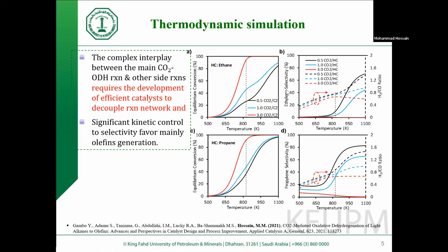To do that, one can consider thermodynamic simulation using the Gibbs free energy minimization approach. Here you can see two sets of plots. The first, A and B, is for ethane, and the second, C and D, is for propane. We can see clearly that as temperature goes up, ethane conversion goes up, and similarly for propane. Also, if you see the three curves, red, blue, and black, with increasing CO2 to hydrocarbon ratio, higher conversion can be achieved at lower temperature. However, the issue is that higher conversion is not necessarily reflected as a selective product. If you see figure B, ethylene as a product, and if we follow the red line, there is almost no ethylene. Most of it is converting into hydrogen and carbon monoxide.